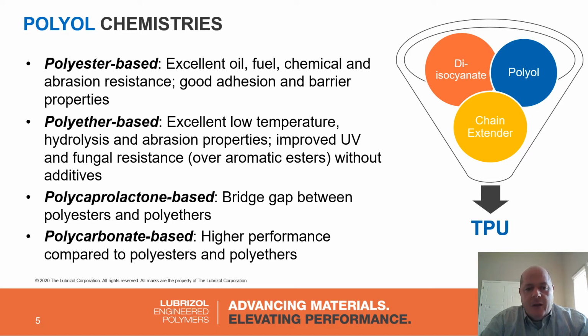For example, polyesters are really good for chemical and petrochemical resistance, where polyethers have good chemical resistance, maybe not as good as polyester, but also have very good low temperature flexibility. We have TPUs that are ductile down to minus 40 C, maybe even below that. Also has good hydrolytic stability and some improved UV and fungal resistance. Polycaps are kind of somewhere in the middle, giving you the most of both worlds. And polycarbonate is a few specialty grades that we have that target high temperature applications.